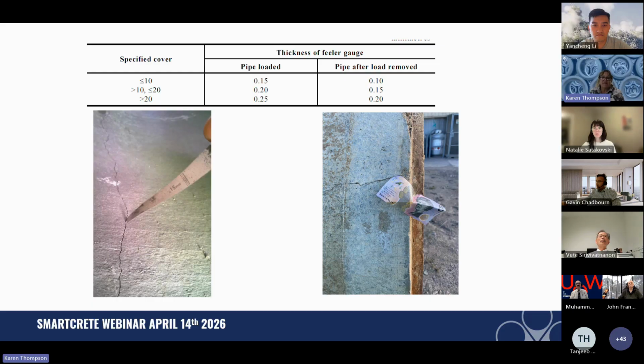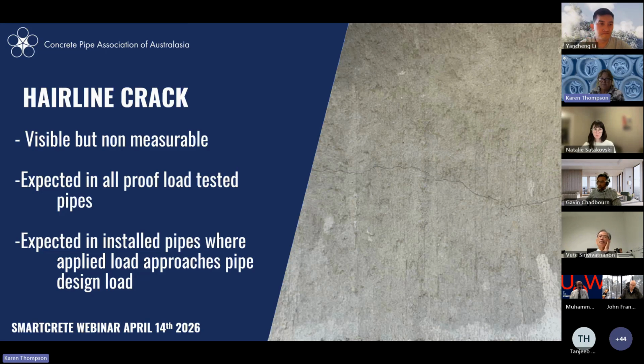Just to give you a sense of allowable crack width, a $5 note is, don't quote me, I think 0.126 millimetres, so it's less than 0.15. When we were doing some factory testing of some old exhumed pipes, I tried to stick a $5 note into a crack and could only just get it in there, and this pipe was ultimately load tested. But it just gives you a sense of the size of allowable cracks.